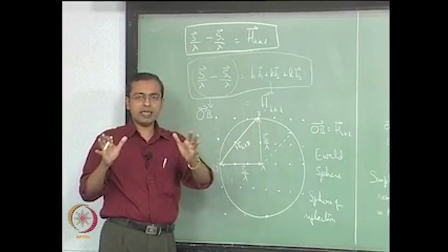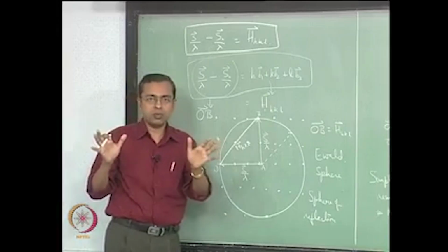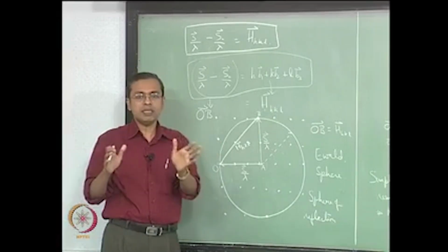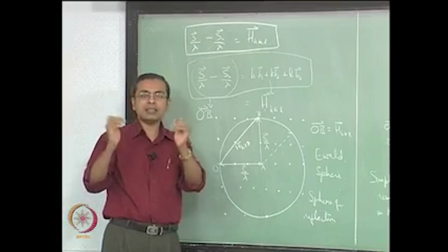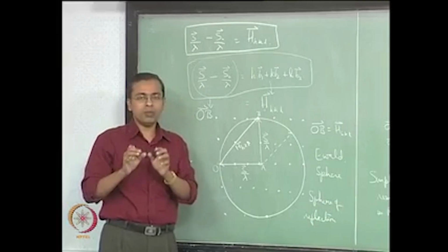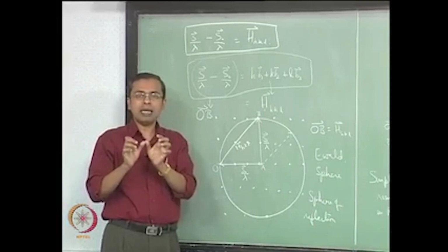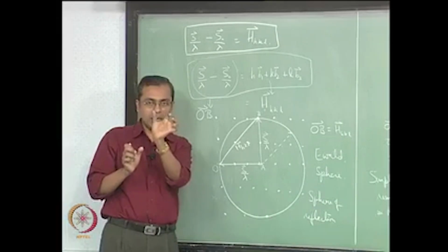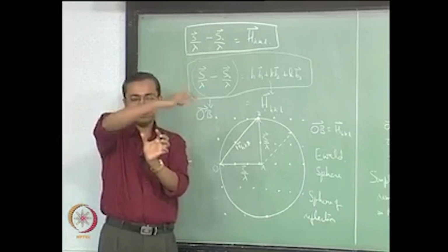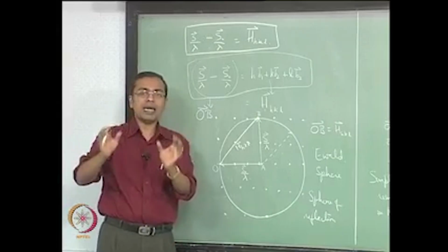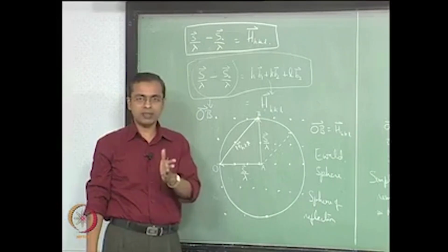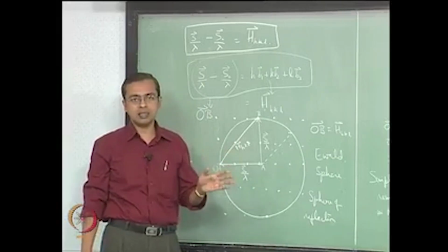This same material, if you want to understand how it is interacting with waves, especially electromagnetic waves, we will have to first represent it in reciprocal space. Its representation in reciprocal space will continue to be a simple cube, except that the dimensions will now be 1 by A. So you make 1 by A, 1 by A and 1 by A in 3 directions, and you build the lattice. That is the reciprocal lattice of the original material you were interested in.